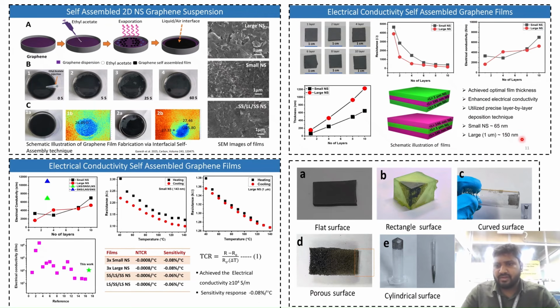With the small nanosheets we achieved 65 nanometers for one layer, and with large nanosheets of 1 micrometer we achieved 150 nanometers for a single layer. We achieved a conductivity of 10^4 Siemens per meter, and we tested it as a temperature sensor, and achieved a negative temperature coefficient of resistance of minus 0.08 percent per degree Celsius. We can coat on any flat surface, rectangular surface, curved surface, porous, and cylindrical surface by this approach. It is very useful for industrial-scale applications.